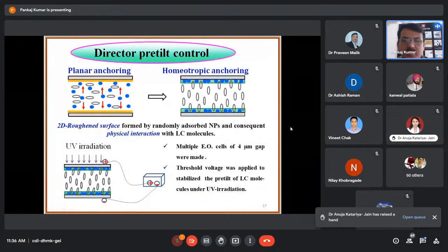So you can see here in this figure the planar anchoring, before we go to the vertical alignment of homeotropic anchoring. Initially, the liquid crystal mixture as well as the nanoparticles are in the planar state. You can see here the liquid crystal molecules are aligned parallel to the substrates, and these are the nanoparticles. So in homeotropic anchoring, how are these nanoparticles modifying the anchoring of the liquid crystal molecules? These nanoparticles are going to the surface. So a 2D-roughened surface formed by randomly adsorbed nanoparticles and consequent physical interaction with liquid crystal molecules gives the vertical alignment of the liquid crystals.